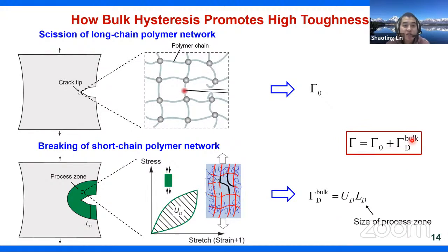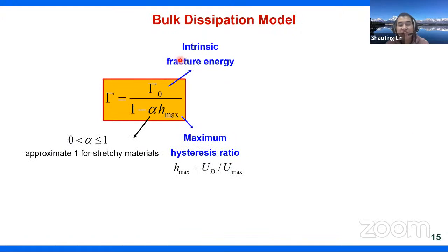And we later derived the scaling equation. What we found is that the total fracture toughness can be estimated by three critical parameters. One is gamma naught, the intrinsic fracture energy. The second is Hmax, the maximum hysteresis ratio. And the third is alpha. Alpha is also a dimensionless parameter which characterizes how fast the material transitions into the high dissipation domain. And alpha approaches one for highly stretchable materials.